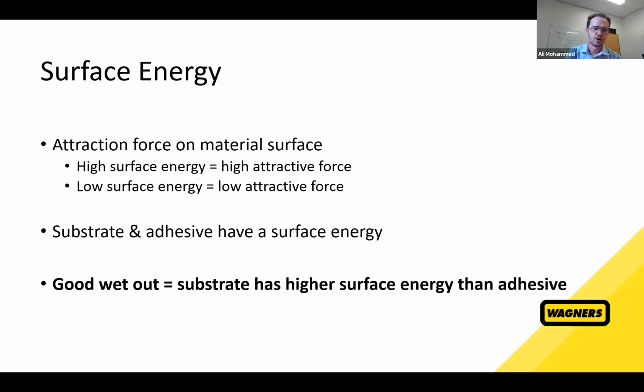In high surface energy materials, the atoms are very strongly attracted to each other, and that results in a very high attractive force on the surface of that material. And the opposite is obviously a low surface energy material where the atoms are not so strongly attracted to each other, and you get a low attractive force on the surface, or a low surface energy. Both the substrate and the adhesive have a surface energy, and it is measurable.